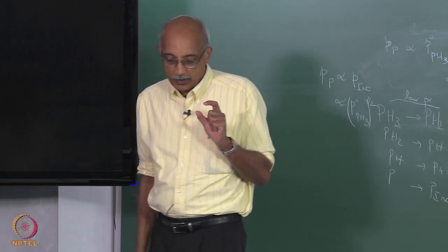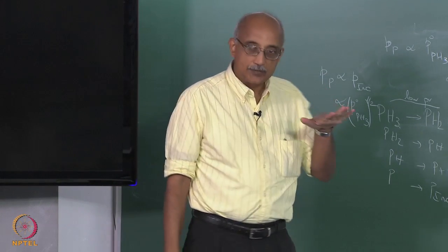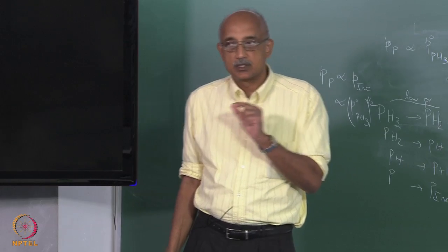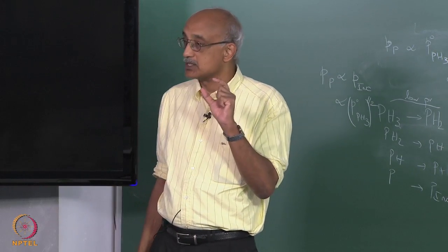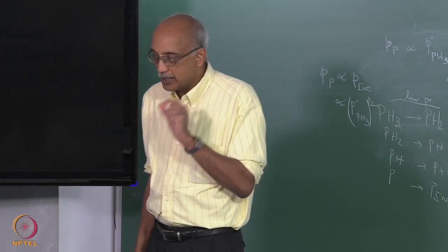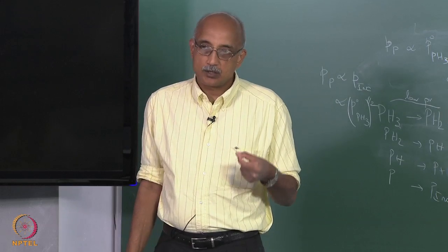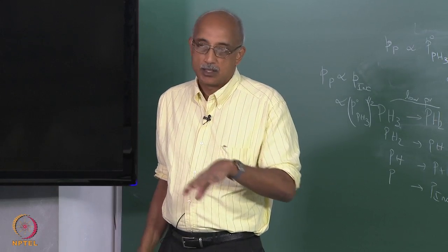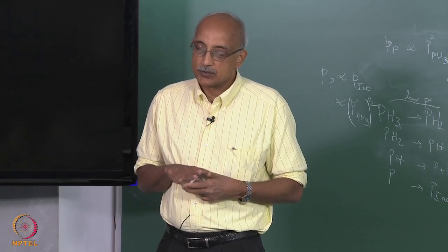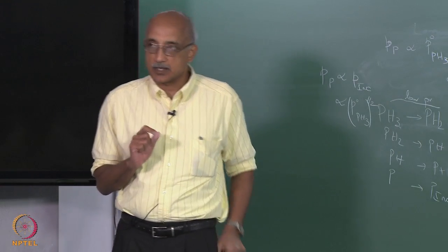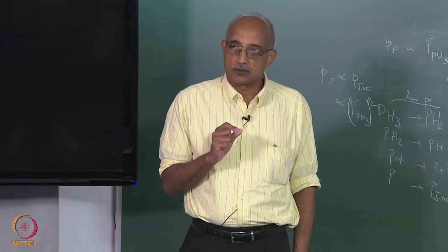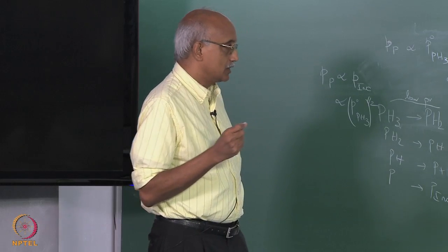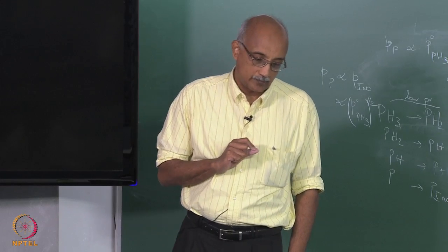But at the same time, the fact that your dopant is present only on the surface essentially means that if you want a CVD film that has a uniform dopant concentration throughout its depth, then either the dopant has to be turned on from time zero, or you have to provide sufficient pathways in your CVD film for the dopant material to diffuse through and equilibrate in terms of concentration. So, the microstructure of the CVD film is also an important factor when you are trying to design a CVD reactor to take in a dopant as a constituent in the CVD film. So, these are some interesting aspects of designing CVD reactors with dopants.